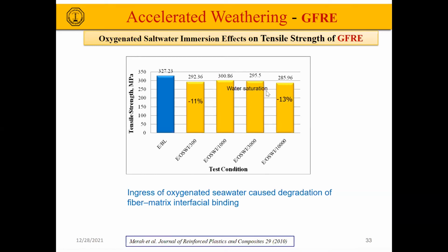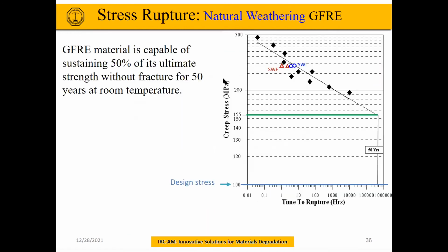If you take into account the scatter, that means after 3 months, it seems like the water uptake has saturated. And we have the ingress of oxygenated seawater, which reduces the strength of GFRE after 300 hours by degrading the fiber matrix interfacial bonding. We looked also at the stress rupture. We have developed an S-T curve, taking into account the scatter of the data. We were able to represent the behavior by this line and extrapolate it to 50 years of service.